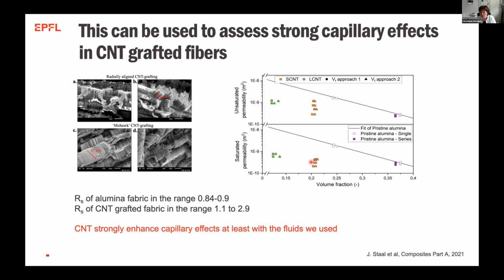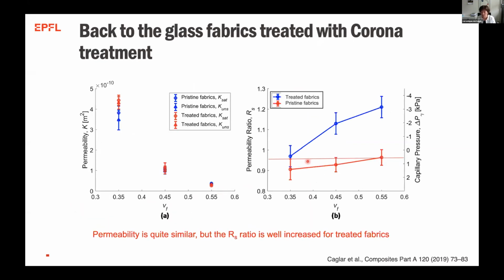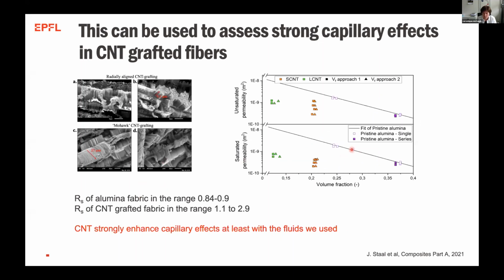We see that when you have these grafted fibers, permeability remains quite low because the nanotubes are there. But interestingly, we found that this ratio for the alumina fabric was in the range of 0.8, 0.9, so for the alumina fabric, the permeability ratio is such that it doesn't really wet. But when we had the grafted fabrics, even though permeability was quite low, the unsaturated permeability was very high compared to the saturated, because we went up to 2.9, a super high ratio. And we used it as a proof somehow that the CNT strongly enhanced the capillary effects, at least with the fluids that we used. We help impregnation thanks to the CNT that actually suck up the fluid like a little sponge as it goes through.